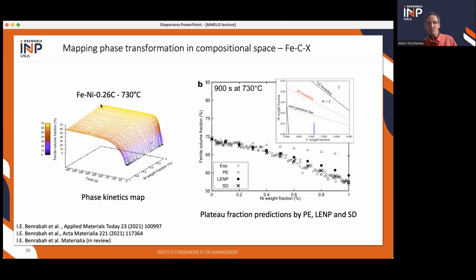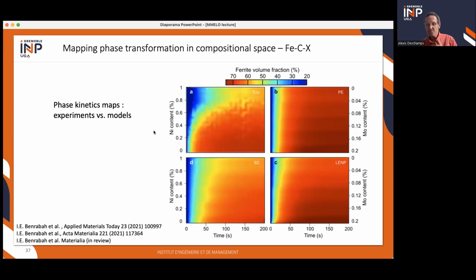And then you can look already at the plateau values as a function of nickel. So this is not kinetics, this is just the steady states. And you can try to model this by solute drag, LENP, or para-equilibrium. And you can actually find the good solute drag parameters to model this data. But of course, you have more than that. You have the full kinetics. And then you can try to test your models with respect to the full kinetic maps.